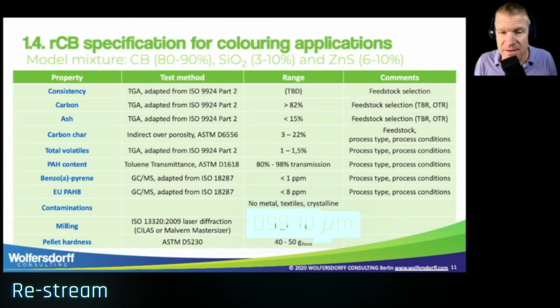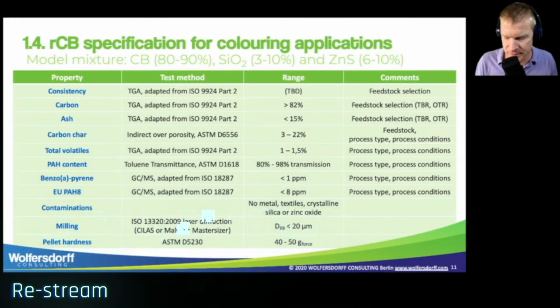How do we measure this? There's an ISO test for it, 13320. This is measured by laser diffraction with a Malvern Mastersizer system. We have to bear in mind that this particle analysis assumes that the particles are spherical, but as we have seen with the normal carbon black, the shape of the recovered carbon black probably is not spherical. So this measurement is an approximate measurement.